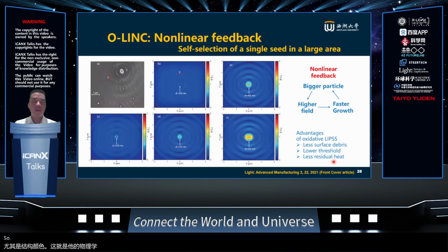In our experiments, and this is a publication from last year in Light: Advanced Manufacturing, it's not really by accident, but almost by accident, that we found that on any surface of materials, you always have small particles of oxide. For example, if you have silicon, you always have silicon dioxide nanoparticles, because part of the silicon is oxidized by the surrounding air with oxygen. And actually, you can see lots of these smaller oxide particles. It's similar for aluminum or metal, copper, anything.